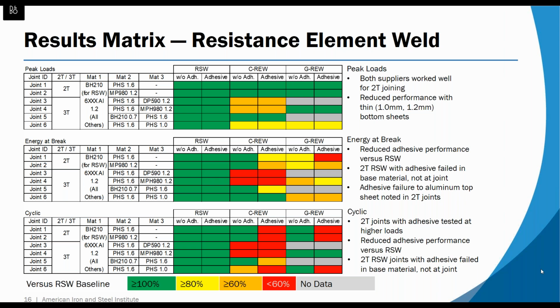In the three-thickness stack, results were a lot more sensitive to the bottom sheet thickness, because with resistance welding it's difficult to get a really good nugget between the mid sheet and the bottom sheet. So depending on the exact stack, some were directly competitive with the resistance spot weld, and others saw some reduction in performance, but were generally acceptable.